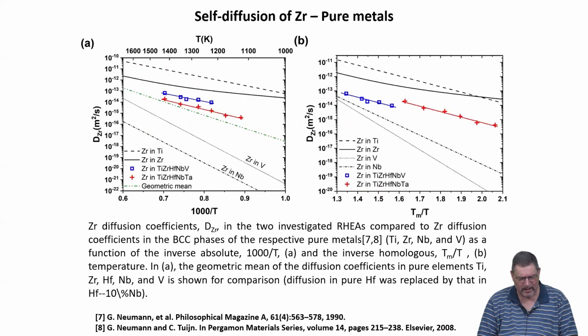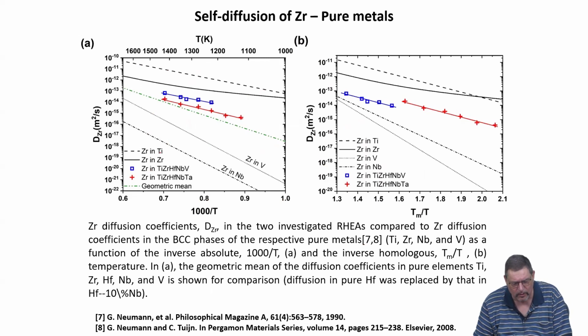Yeah. This is an instantaneous source solution, and this is then the Harrison B-type classification. Obviously, because you see very pronounced grain boundary and volume contributions, this needs to be applied. We then analyzed the zirconium diffusion. So zirconium was the tracer. And you can see here a comparison again of tracer diffusion, radio tracer diffusion of zirconium in the pure elements titanium and zirconium. This is the black solid line as well as the dashed line, as compared to data for the two alloys as just indicated.